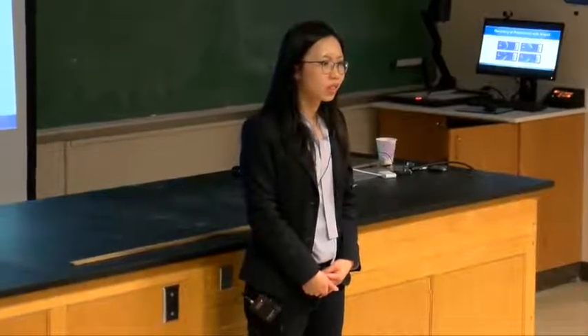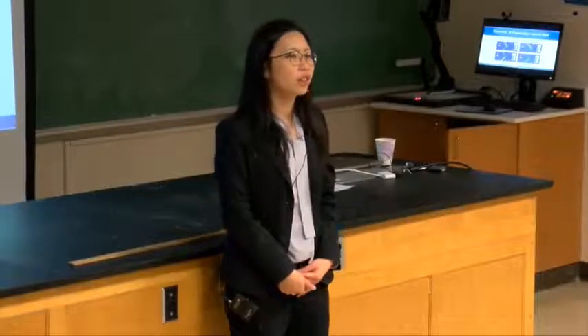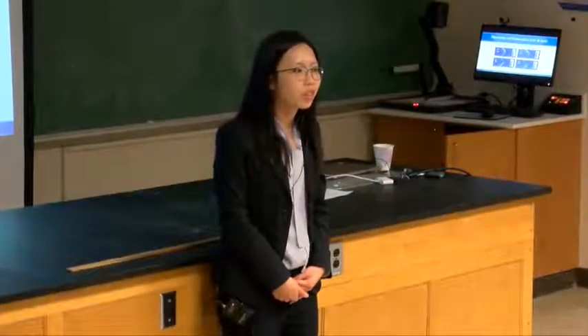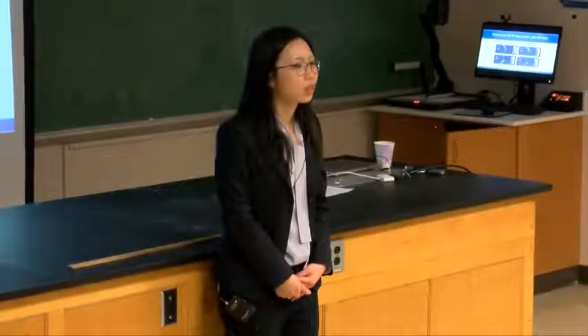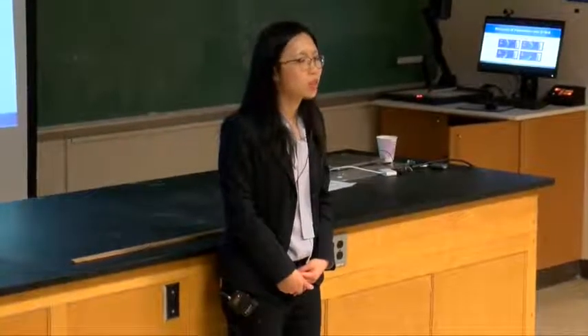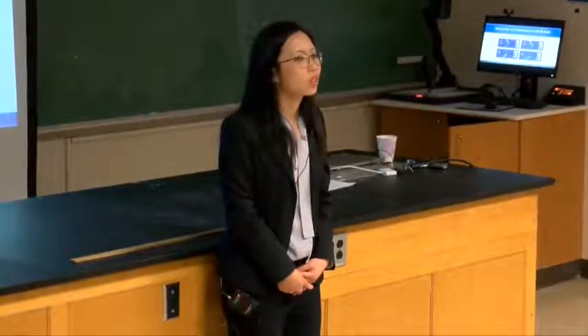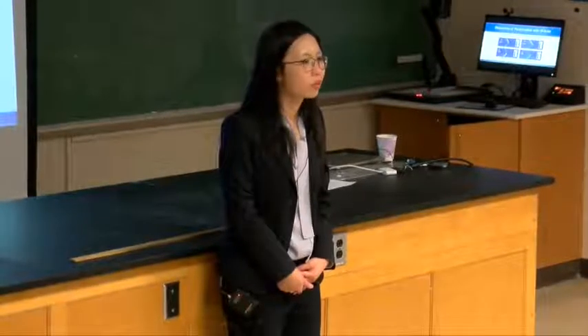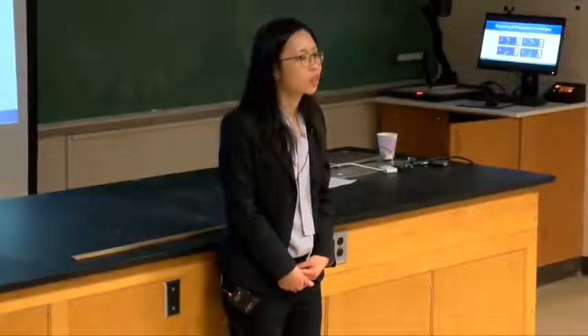One comment about that. If you have a shallow defect, you would expect the defect to have the character of the host material, right? Would that be a possibility to trap it in a shallow defect? A shallow point defect. Some transition levels are very close to the conduction band or valence band, so it looks more like an effective mass state of your bulk material. It has all of the properties of your bulk material. Would that be a possibility or not?